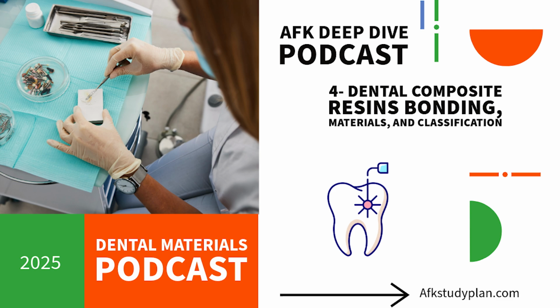It can, yes. And you need the curing light unit itself, which is an expense, plus eye protection is essential for everyone. And how you use the light matters too, doesn't it? Distance, angle? Oh, hugely important. Critical for success. You need the right wavelength of light for the specific composite, usually 480 nanometers for CQ. The light tip needs to be super close to the resin, almost touching and perpendicular to the surface. And steady. Rock steady for the full time. And dentists need to regularly check the output, the intensity of their curing light, to make sure it's delivering enough energy. Not enough energy means incomplete curing, weak filling. There are lots of different light types too: LED, halogen, plasma arc, lasers.